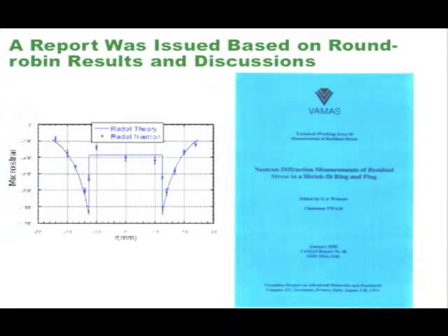And in it, a number of potential pitfalls were identified in making reliable residual stress measurements, such as making sure that your scattering volume is fully embedded in the sample, and so on and so forth. So this is a very useful document. I believe you can download it from the web.